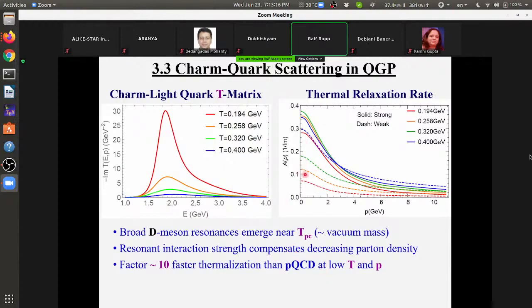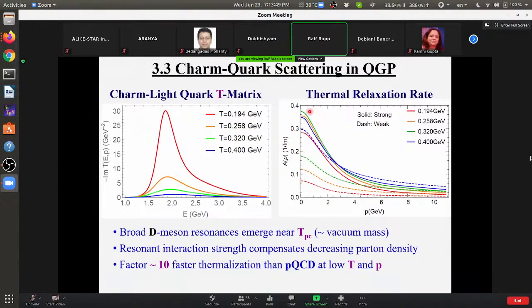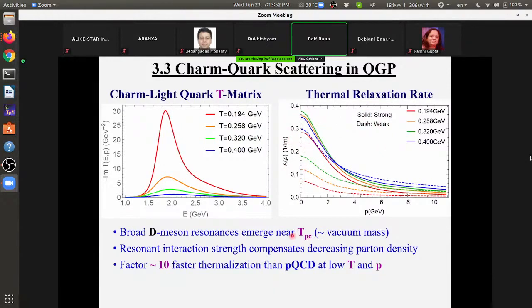Although the parton density increases a lot when you go, say, from 200 to 400 - the parton density in the QGP increases by a factor of 10, roughly, maybe 2 to 3 or more - the relaxation rate in this calculation only increases by a few percent. The reason is the compensation between increasing density in the medium and decreasing interaction strength. So at the end of the day, in this strongly coupled solution, shown as solid lines, these don't depend very strongly on temperature because of the build-up of very large interaction strengths as the parton density drops toward TC.